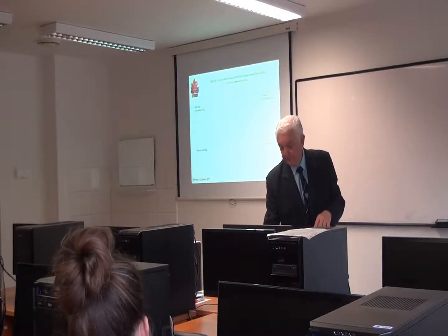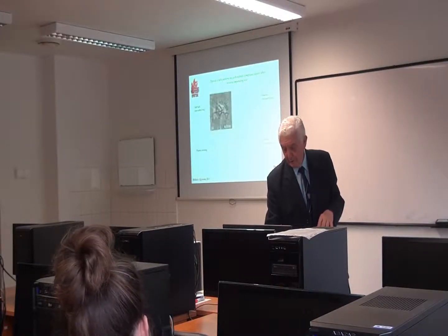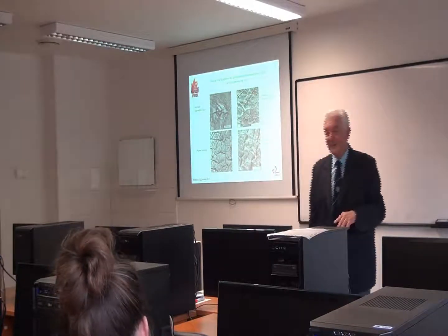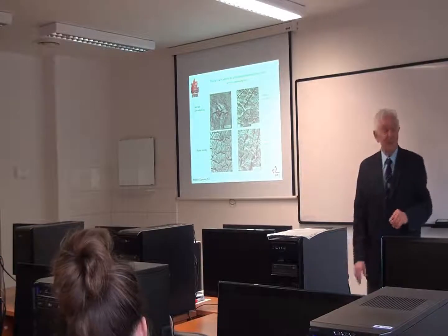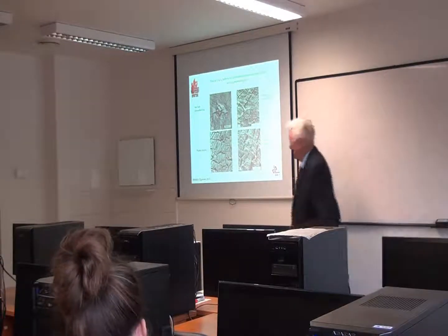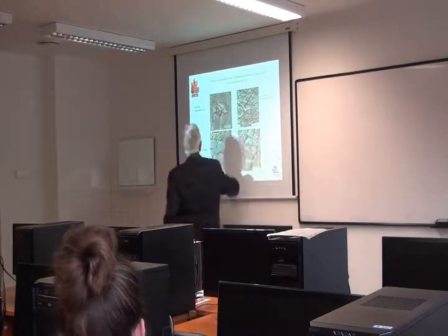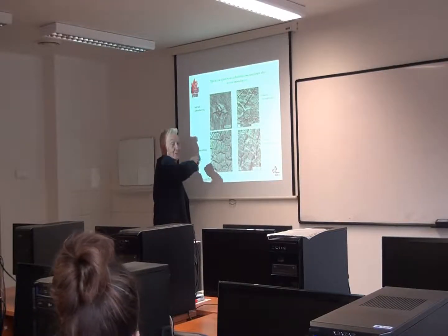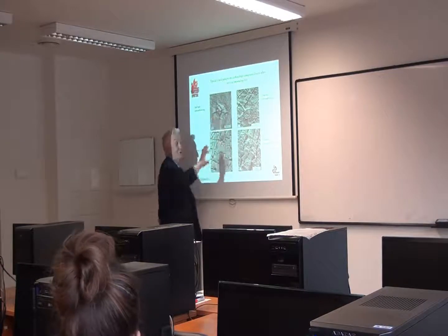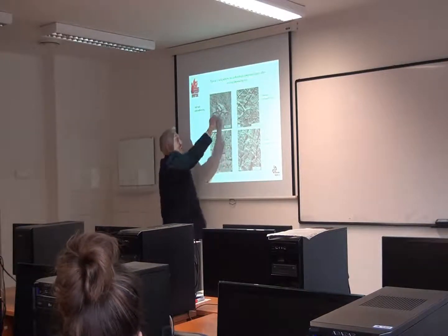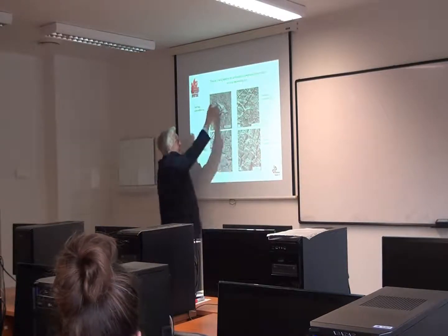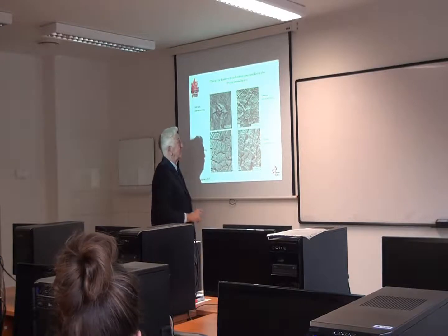And there are very different possibilities. I will just show you these four, and then I finish this part because we can go in different directions. This is a salt bath. What you see is a salt inclusion, and at a salt inclusion, when you give this deformation, it will explode, starting from the salt, and then the specific network will form.